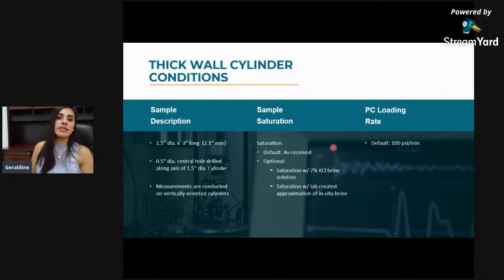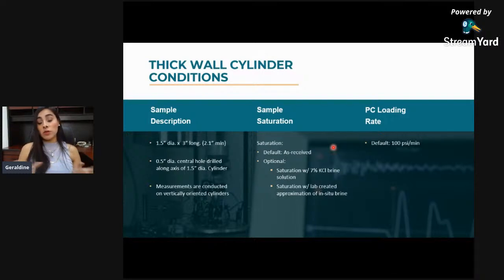Okay, then we have the hollow cylinder. For this test, you want samples of 1.5 inch diameter. We use here the same length to diameter ratio of 2:1. So the optimal will be 3 inches of length, but the minimum could be 2.1 inches of length. So in this block, you will drill a central hole of 0.5 inch diameter, and the measurements are conducted also in vertically oriented samples.